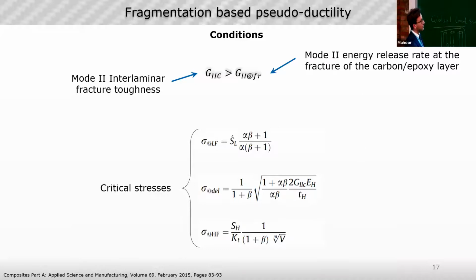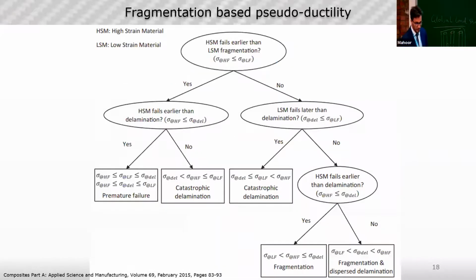This condition summarizes perfectly what I said before, that the interface property counts a lot in the material. So not only the thickness, which is summarized in the formulas to generate the curves in the damage mode map, and the thickness is included in the alpha and beta parameters, which are the ratio of the thickness and the elastic modulus of the 2 materials. But this condition counts a lot too.